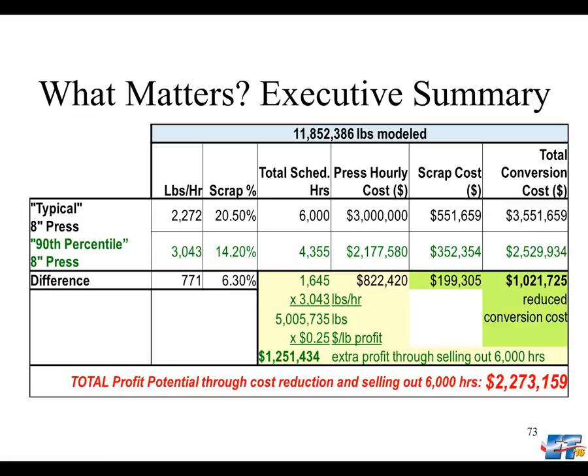So if I look at the first line on this chart, typical 8-inch press, it was 2,272 pounds an hour, where the 90th percentile extruder was at 3,043 pounds per hour, and the scrap next to it. But if you continue to look over to the right, you'll see when run through my model, it shows that we're going to save 1,645 hours of production time because of the higher pounds per hour and the lower scrap rate. That'll save us over $800,000 in costs.